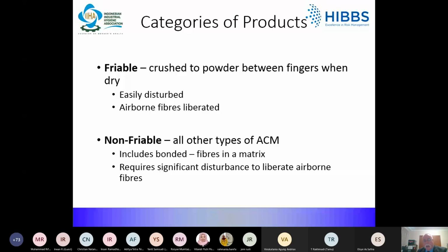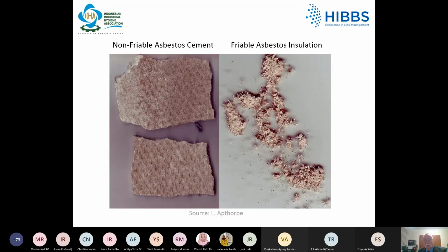Non-friable materials, on the other hand, there's generally less asbestos in the material. It's bonded into the matrix, and it requires significant disturbance to liberate airborne fibres. And if you think about things like asbestos cement sheet, the only way that you can liberate fibres from that is by disrupting the matrix by running a power saw through it or something like that. So on the left, you've got non-friable fragments of asbestos cement, and on the right, you've got friable asbestos insulation.